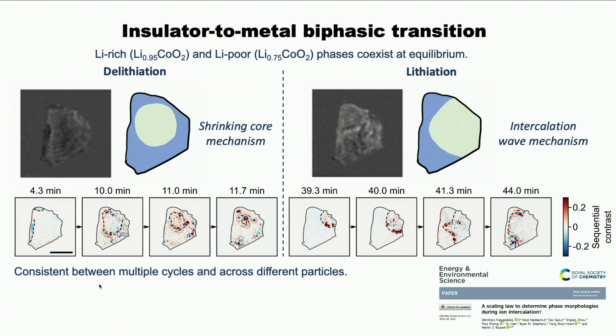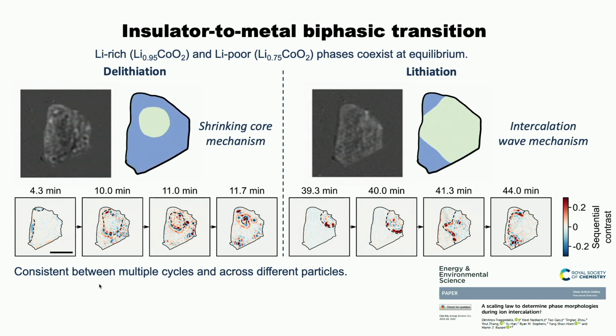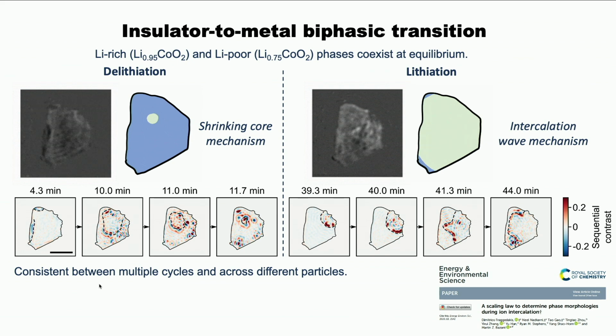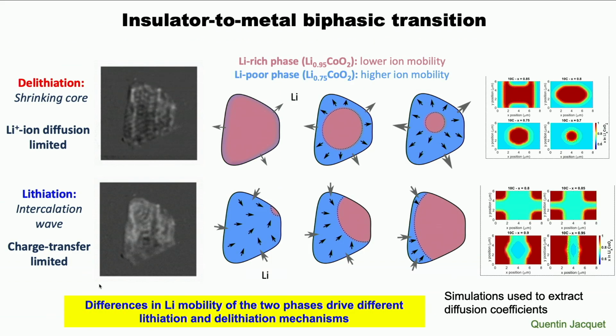So what's going on? There was this beautiful paper by Martin Bazant and Yang Shao-Horn, who had examined different mechanisms and thought about why you would get different types of intercalation processes. And they separated these two mechanisms, the so-called shrinking core mechanism and an intercalation wave mechanism. And if you look at our particles, this is exactly what's happening. Here you've got a nice shrinking core. This is shown in snapshots. But on the way back, you're lithiating and you're nucleating one thing and it's moving across. So why do you have two different mechanisms on charge and discharge? What my former postdoc Quentin did was to try and model this with continuum modeling. And we just think about why this might happen.